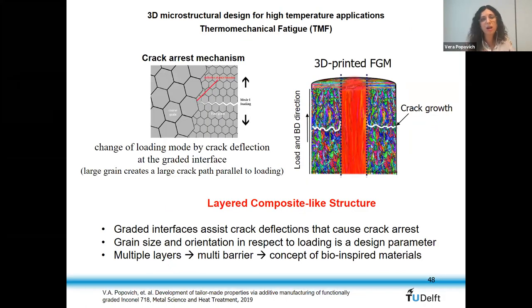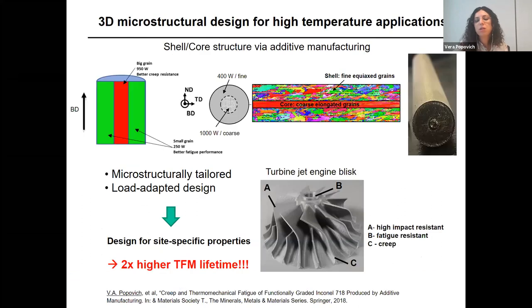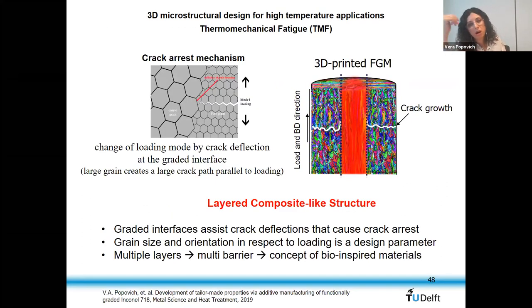With this, we looked at thermomechanical fatigue. Again, this is something that we will not cover with you guys, but this is a fluctuation of both stress and temperature. We cycle the temperature from 350 to 650 and also the stress level, something that you would experience in the jet engine, for example, at the most extreme points, so start and shutdown, takeoff and landing. And what we see is that with this kind of technique we improve twice the lifetime compared to the cast and wrought material.